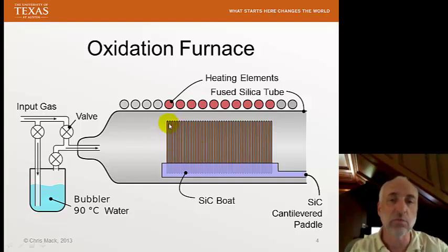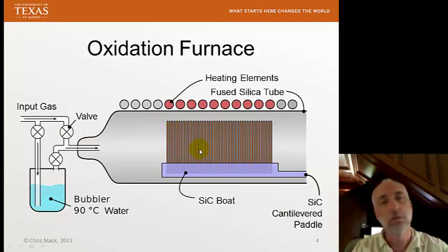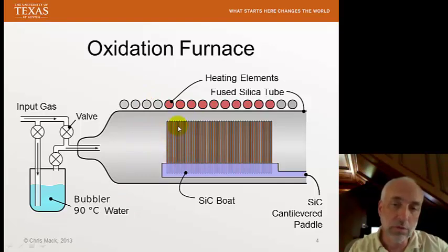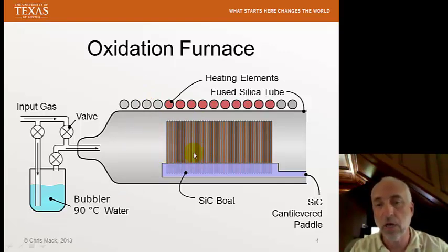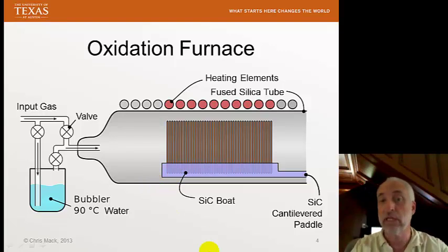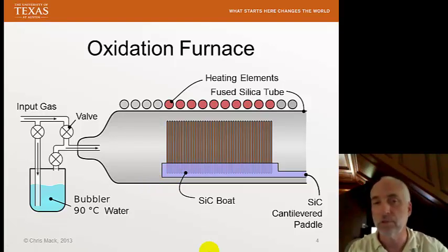It's important that this whole assembly never touches the sidewalls. We're growing material on the wafers themselves, but we also get reactions at the fused silica tube surface. If our boat ever hit the surface, it would generate lots of particles and be a disaster from a defect perspective.